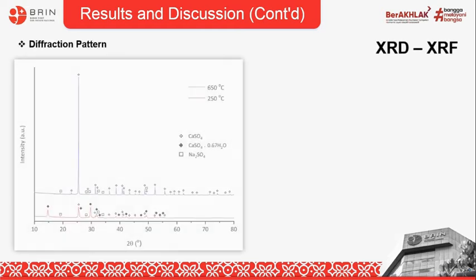The phase composition of the powder was analyzed using XRD. The diffraction patterns were stacked for comparison as shown here. Compared to the ICSD pattern list, the sample heated at 250 Celsius degree consists of two major phases of calcium sulfate, hemihydrate and anhydrate, while the calcium sulfate was only found in the anhydrate phase after heating at 650 Celsius degree, as expected.